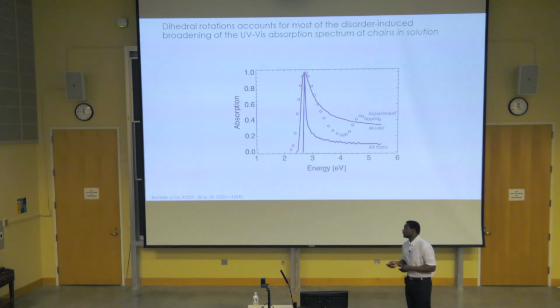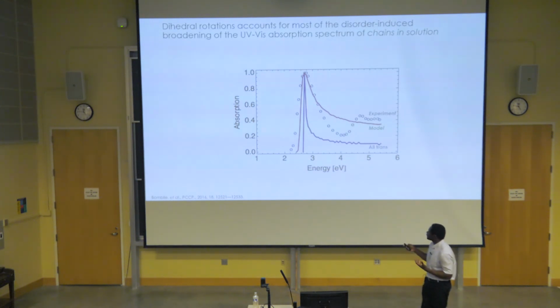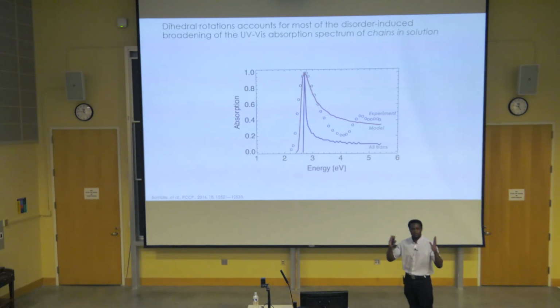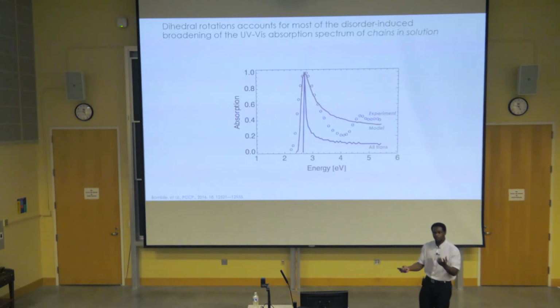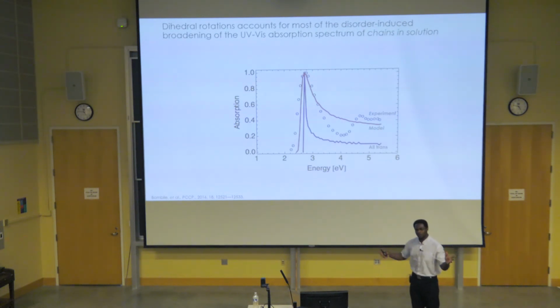And the point of this graph here is why is the absorption spectrum broad? It is broad because when the measurement is done, you don't have a single polymer chain, but many polymer chains in solution with different configurations. So the broadening is a result of disorder within the material.